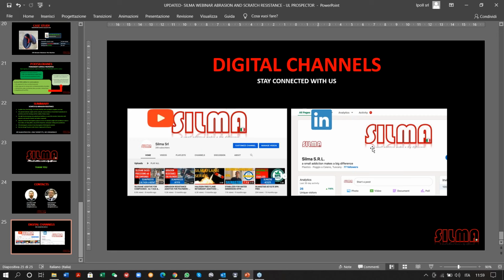Let me answer one last question because it's 2 minutes to the end. I want to thank everyone, and I will also reply to all the questions by email, as I already mentioned. Okay, what Silma additive do you recommend to improve the abrasion resistance of HDPE PoE cable compound? This is our main market, main application, which is cable compounds. So for HDPE PoE cable compound, Silma process AL1142+. AL means based on LLDPE material, and it will be completely mixable with the HDPE and PoE, and the dosage recommended is around 2%.